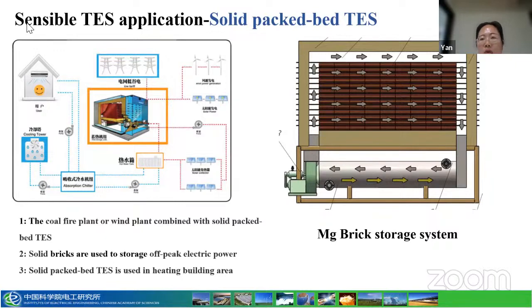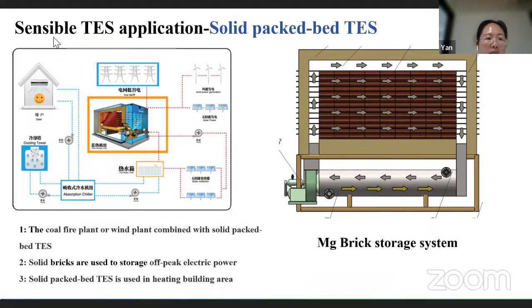And also solid brick energy storage is used very popularly in China. They use magnesia brick to store the heat, because the brick can reach very high temperatures, maybe more than 1,000 degrees. So the off-peak electricity can be stored in the brick. And when we want to use the heat for heating buildings, we can discharge the heat by air or water.